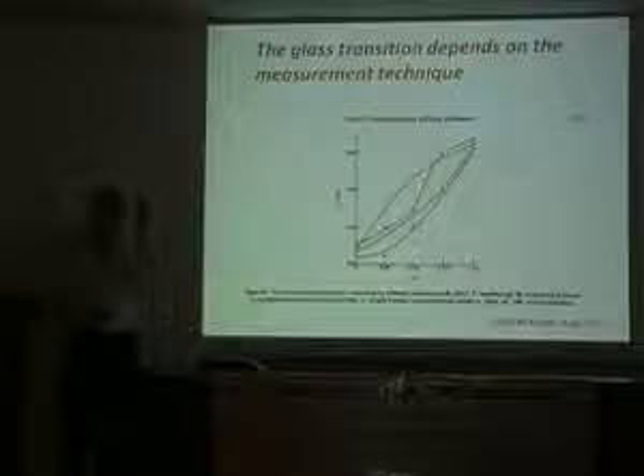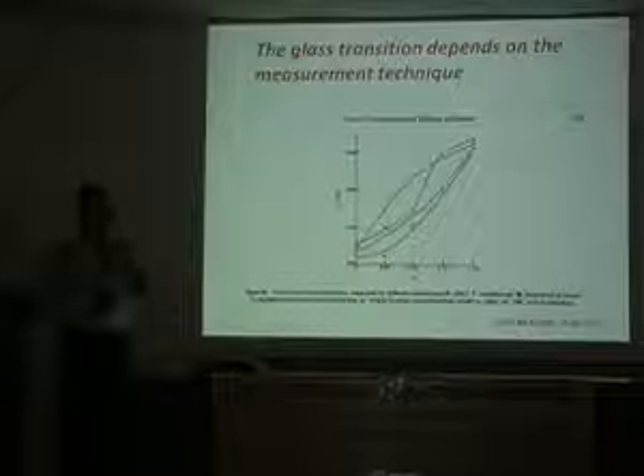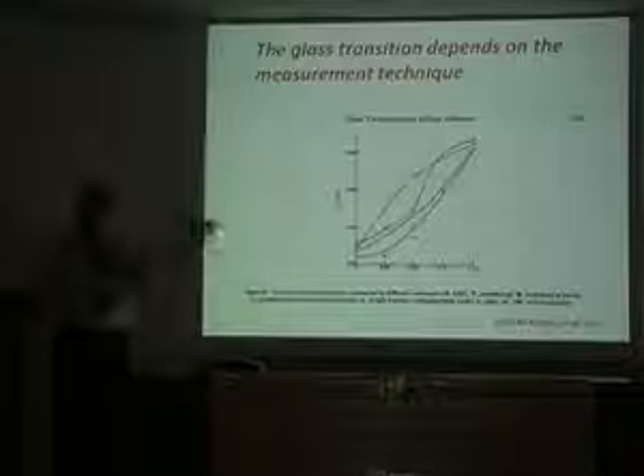And sorry, in each case, how is it measured? I mean, how do you say this is TG? Well, when somebody does a DSC, you know how they do that, right? You get the break in the heat capacity. When you do a dynamic mechanical measurement, there are different estimates of the TG. Some people will measure the peak in tangent delta. Some people will measure the peak in G double prime. Some people will measure the midpoint or some point in the reduction in G prime, as a function of temperature at a scan rate, and it's mixed because you have a scan rate convoluted with an oscillatory frequency, right? And both of those affect what you measure.